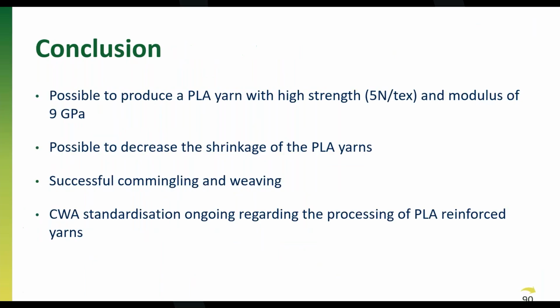And to conclude, so we were able to produce PLA yarns with a high strength, 5 Newton per tex, and a modulus of 9 gigapascal, so far exceeding the requirements set at the beginning. We could decrease the shrinkage of the PLA yarns with the two-step drawing process, and we can successfully commingle and weave all those yarns. We did some standardization also, and one note I want to end with is that the